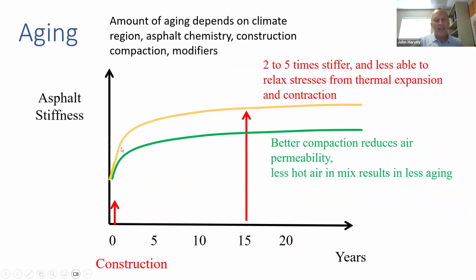For the initial stiffness, we have a rapid increase in stiffness over the first 5 years, and then we tend to reach a steady state increase in stiffness when you get out to about 15 years, depending on the climate region. A hotter climate region will get there faster: Central Valley, desert, Inland Empire. A cooler region will get there slower: North Coast, up in the mountains, South Coast. But you get 2 to 5 times stiffer. That gives you an idea. It's 200 to 500% stiffer. And we're losing that ability to relax as well.